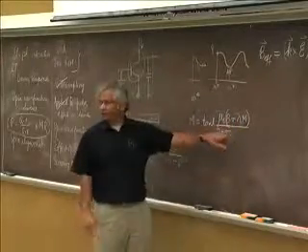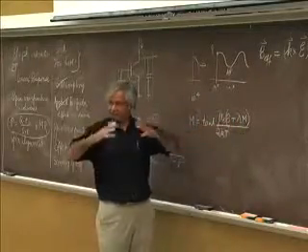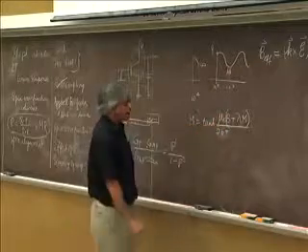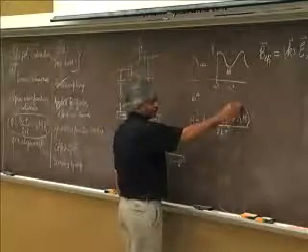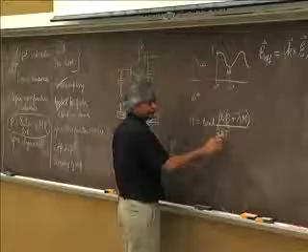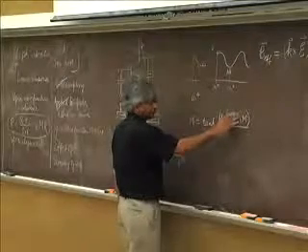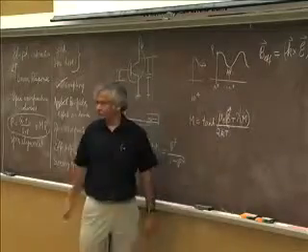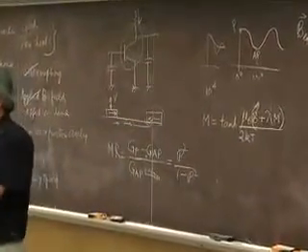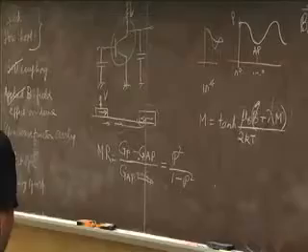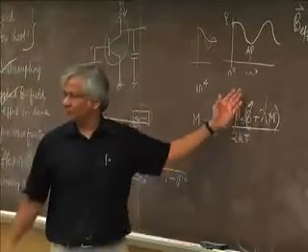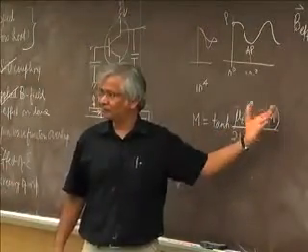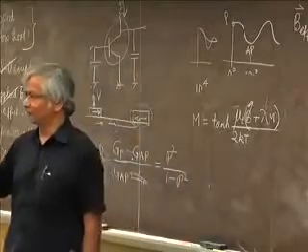And so you could have a correction due to that, as if there's an internal field of some kind. And then you show that if lambda is big enough, compared to this temperature, then even when this is 0, you could have a solution. And so that is why it by itself becomes a magnet. So this would be in the sense of a self-mean field, almost. This is the mean field theory of ferromagnetism, almost.